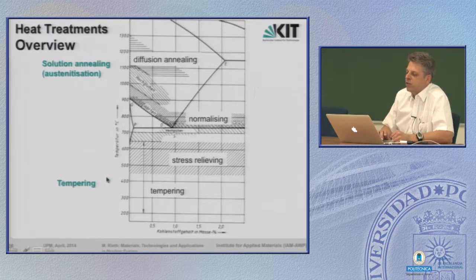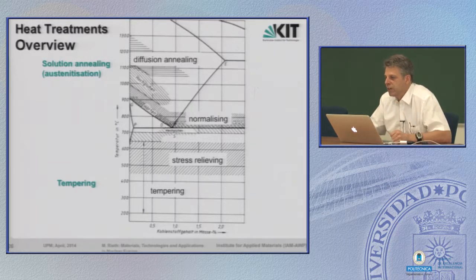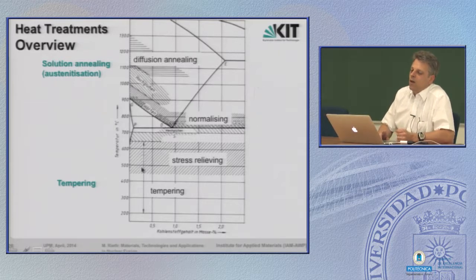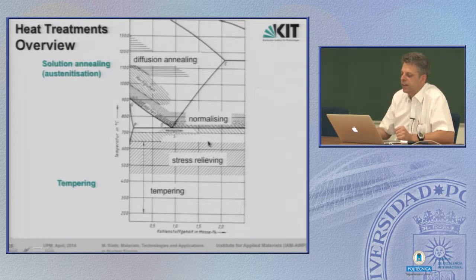Then you quench down. If you have quenched down, there are other heat treatments, which I name tempering, to distinguish from annealing, which means solution or whatever. Tempering in a certain temperature range relieves the stress in the steel. Due to fabrication routes, there could be many internal states of stress. If you temper them in, let's say, that temperature range, 500 to 600 C or so, you relieve these internal stresses, but without changing anything else.